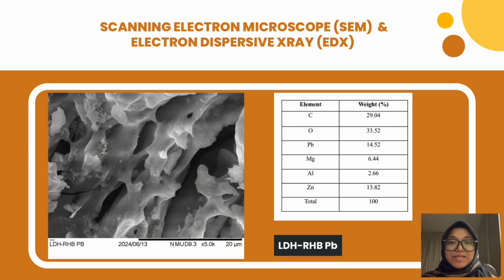Lastly, we examine the composite after absorbing lead ions in lead SW samples. The SEM image shows significant morphological changes, with more defined and deeper cavities and pores formed on the surface of the LDH with rice-husk biochar. The EDX analysis confirmed the presence of lead with a composition percentage of 14.52%, and the structural reorganization and high lead content indicate the successful absorption of lead ions, which enhances the composite functionality for heavy metal removal.